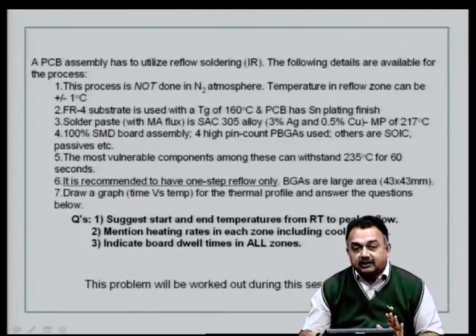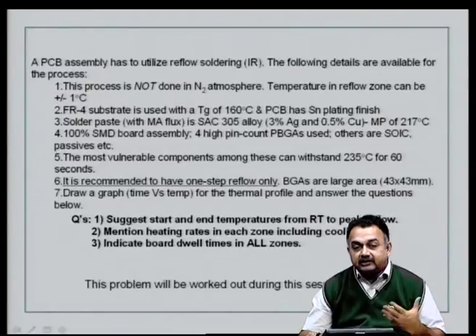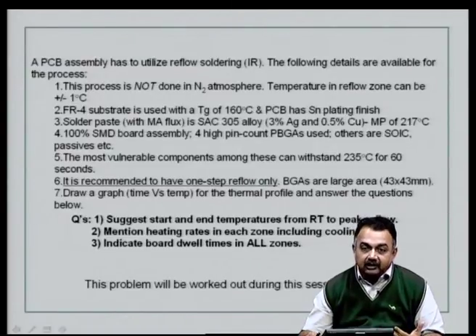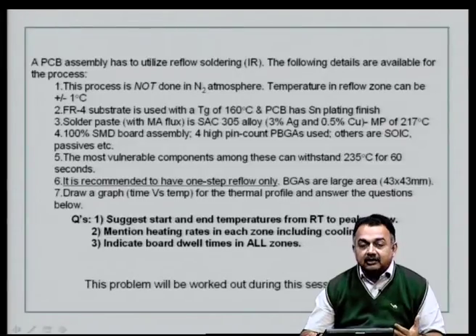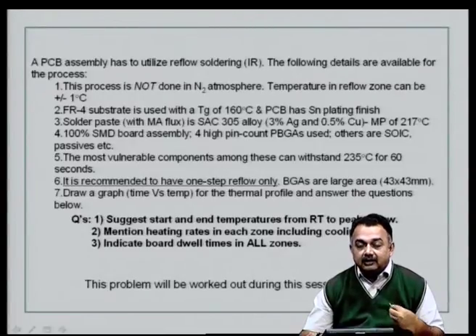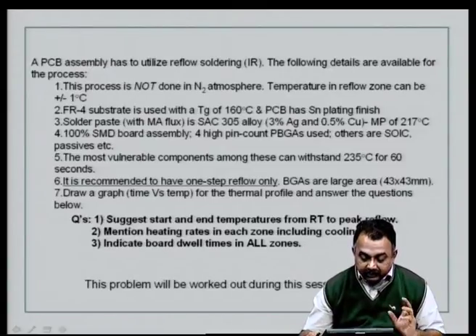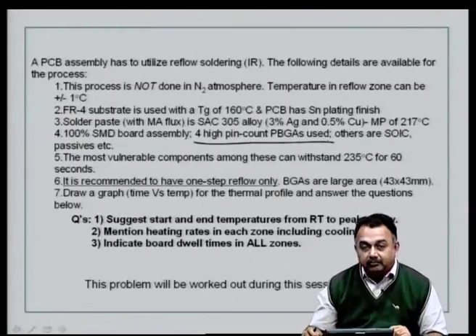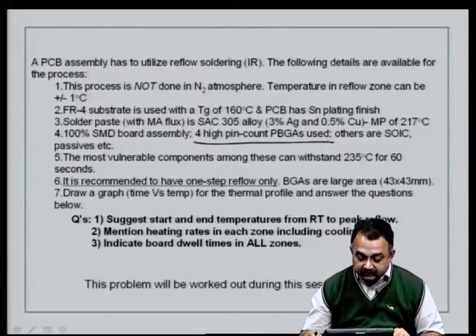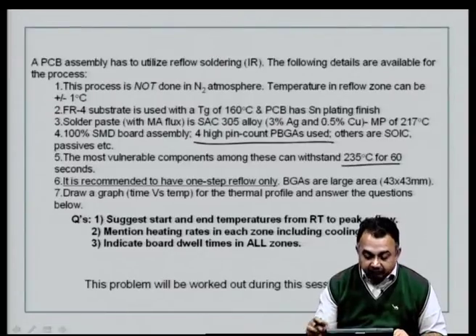The reason for giving information about high-pin-count PBGAs — say 800 solder balls — is that you have to give more residence time for all the flux under the plastic BGA to get activated. You must also give more residence time in the reflow zone so you do not end up with 30% of solder balls not attached or reflowed. The most vulnerable component among all components can withstand 235°C for only 60 seconds, which clearly defines your peak reflow zone residence time. It is recommended to have a one-step reflow only, and BGAs are large — 43×43 mm.